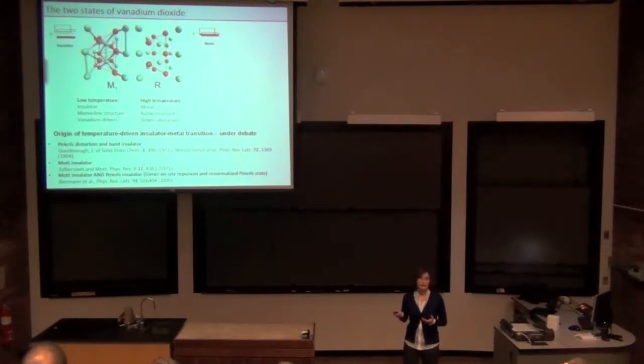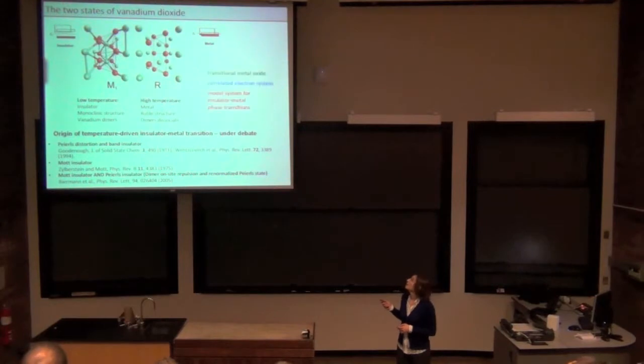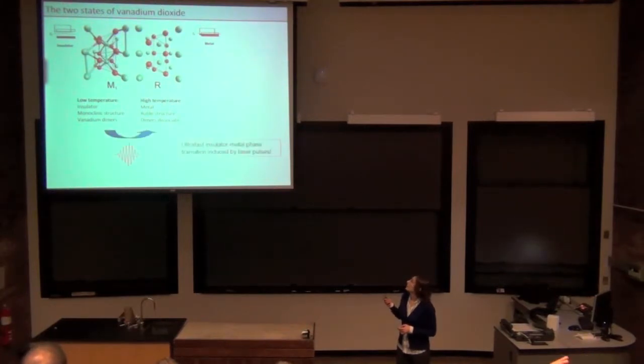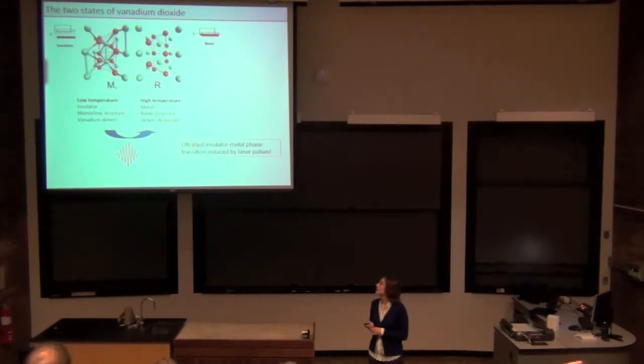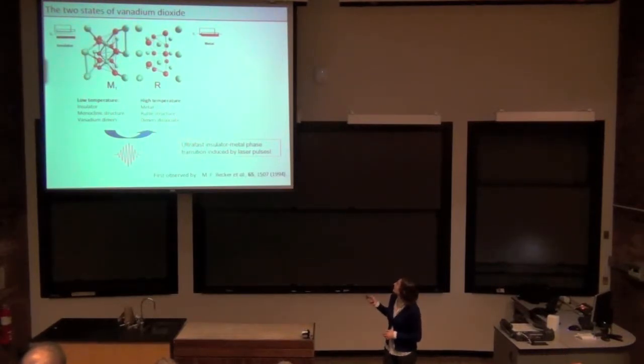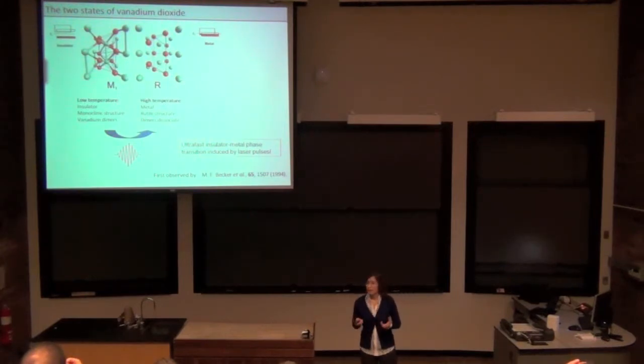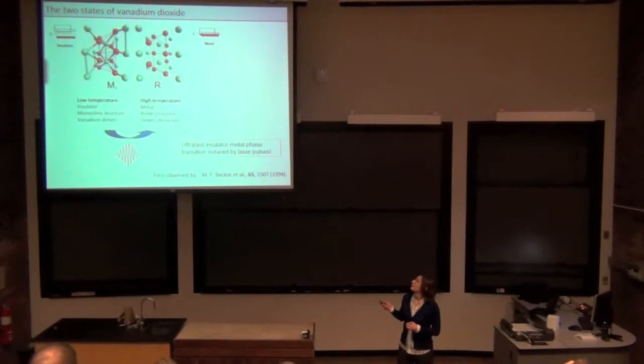insulating state. This is already complicated enough, but the story gets even more interesting, because in addition to temperature, it turns out, as was first observed in 1994, you can drive this transition from the insulating to the metallic state by an ultra-fast optical pulse. What happens then is that this optical pulse, of course, excites an electron out of this dimer state, and we see this ultra-fast transition to the metallic state, which then lasts for nanoseconds.